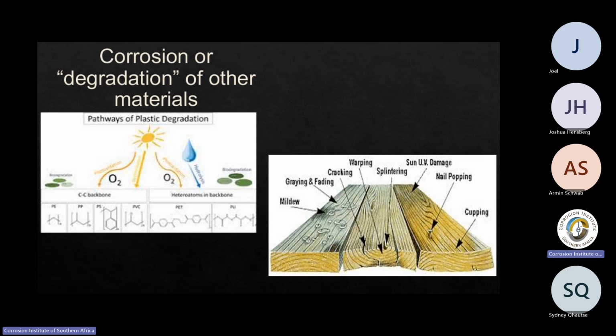But what affects plastic? You've got UV. As soon as that stuff gets into contact with high environmental conditions, temperatures, and so forth, it can start breaking down certain elements in the actual polyethylene. And polyethylene is a perfect mold release. They actually put it inside things that you don't want it to stick to. What do people do when they do some spray painting? They take a black plastic packet, polyethylene, and they mask it and you paint on it. You can actually take the paint and peel it off. It doesn't stick to it.